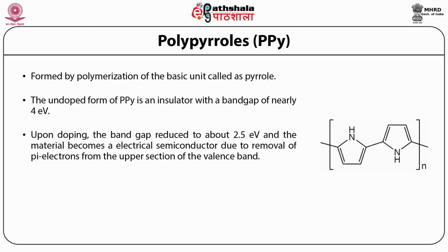One needs to dope the polymer polypyrrole to achieve a conducting polymer, which is typically achieved by the oxidation of the polymer, that is by p-type doping. In the case of p-type doping, the process can be carried out electrochemically, which helps in achieving high purity conducting films of the polymers easily.